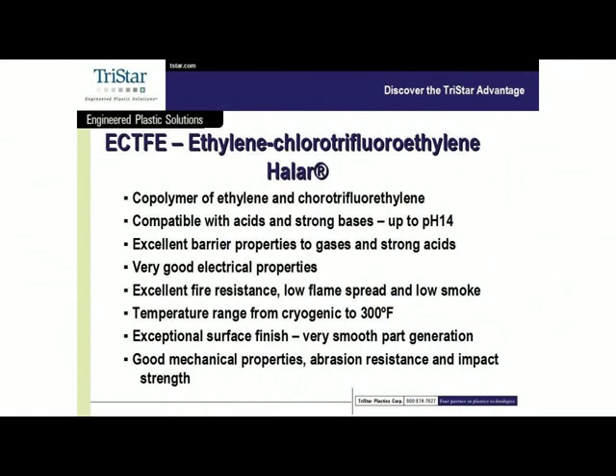The next material we're going to look at is ECTFE. This is ethylene chlorotrifluoroethylene, better known in the industry as HALAR. This is a chemistry where we're taking a copolymer of ethylene and chlorotrifluoroethylene and combining them. This product is very compatible with pretty much the whole pH range, especially in strong acids and strong bases. It has very good barrier properties. It's very non-porous, and so as a barrier material in gases and especially in strong acids, it's a very, very good material in that media.